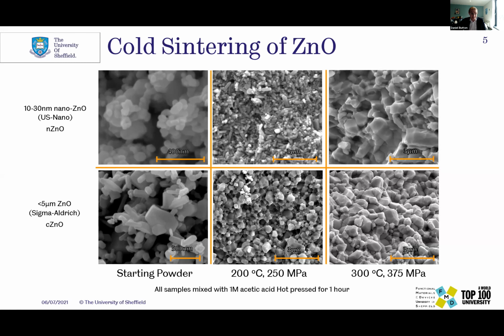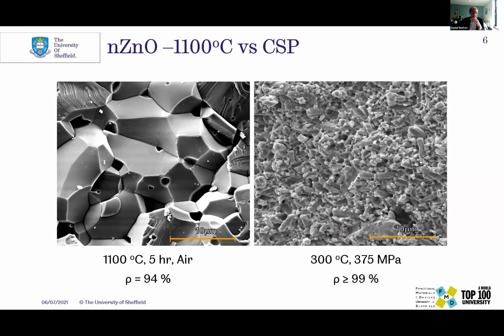Next slide, please. On the left you can see a conventionally sintered zinc oxide material. It's usually sintered at 1100 to 1500 degrees. Extremely large grains are produced, but the pores are still very large, so you'd still need a bit more energy to get much higher densities. The cold sintered material on the right has a much smaller grain size, but has had the benefit of that compression during the hot pressing, and so achieves consistently above 99% dense, near theoretical density. But again, you've got this columnar structure coming through.